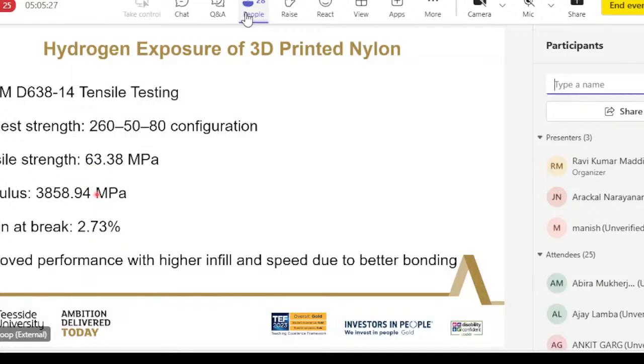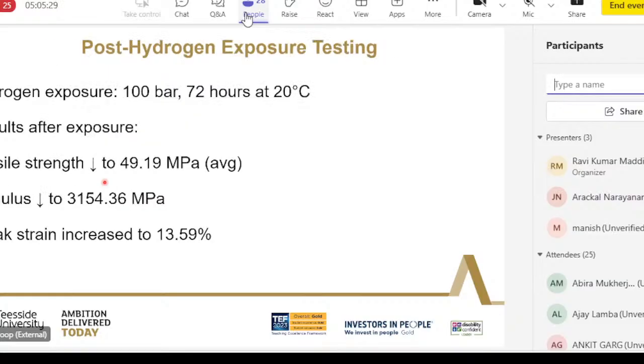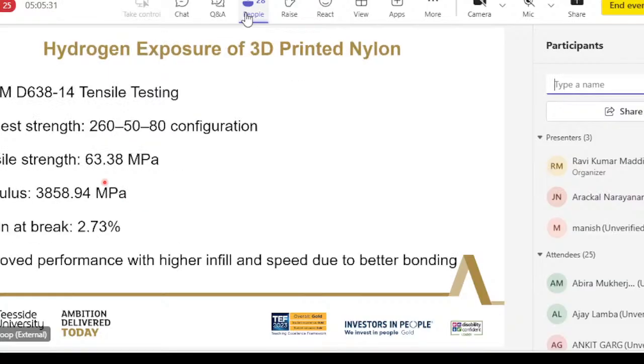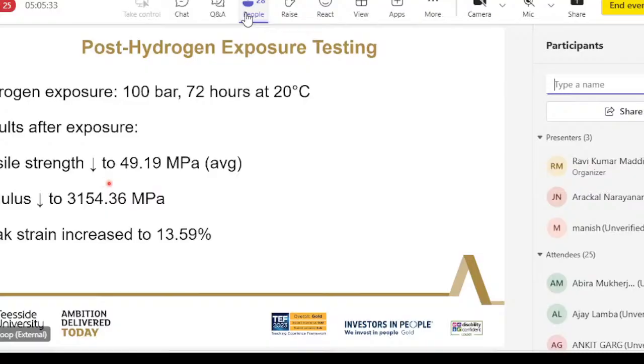After exposure to around 100 bar of hydrogen for 72 hours at 20 degrees Celsius, we could see that the tensile strength dropped to 49.19 megapascal, the modulus dropped to 3 gigapascal, and the break strain increased. So it means that the material is getting more softened as we are exposing it to hydrogen conditions.